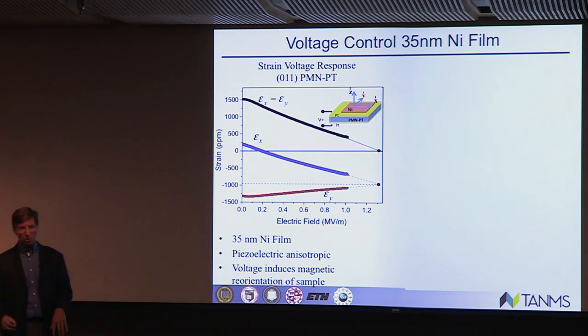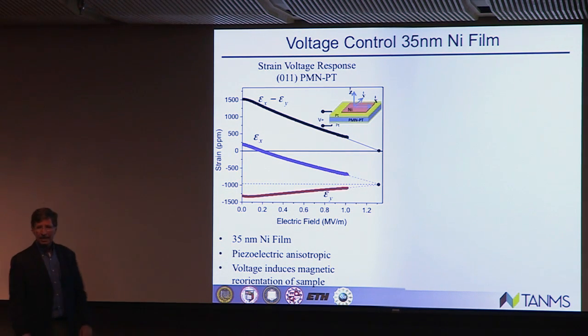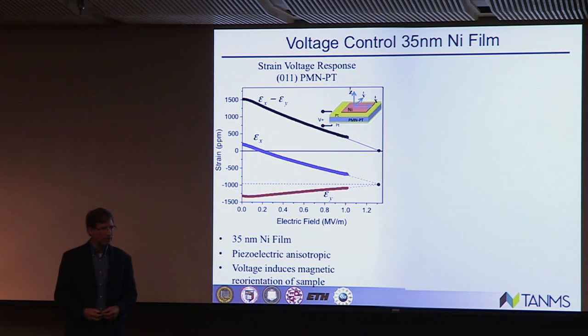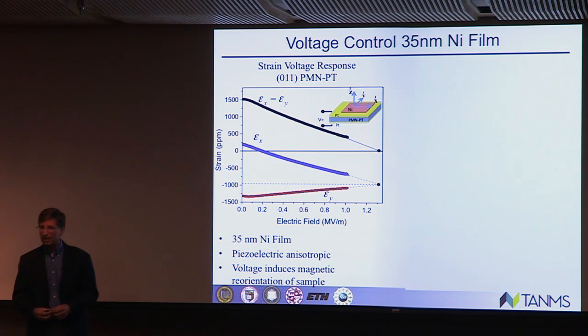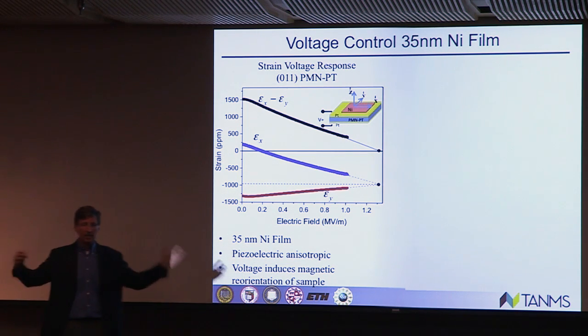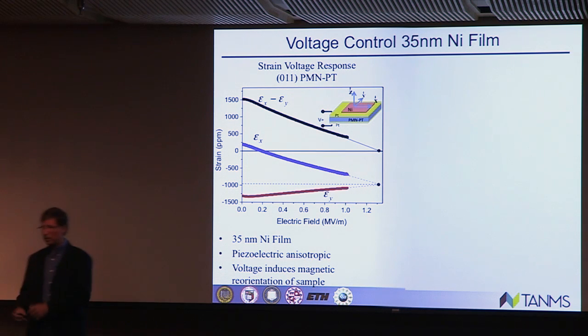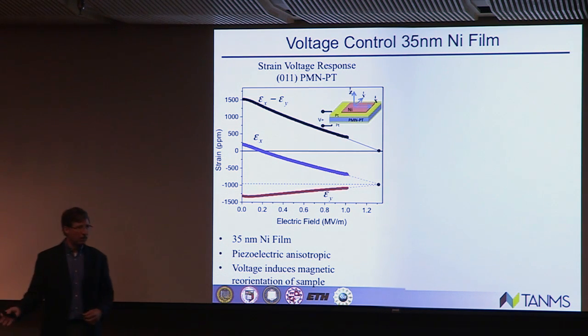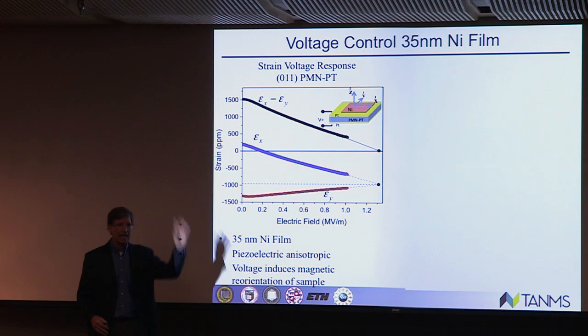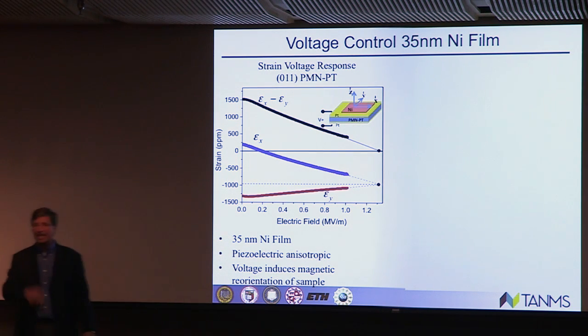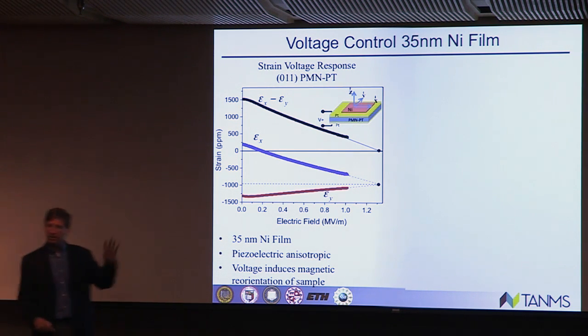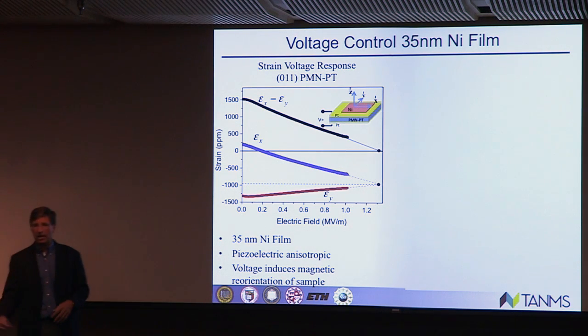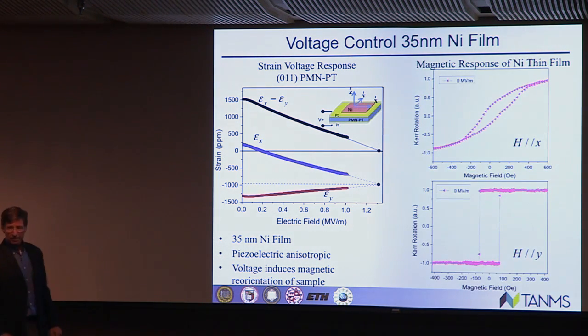Now that's very important. Now the other thing I want to point out is what magnitude strain are we looking at? Now some of you may not hear strain that often, so let's just talk about percentages. We're talking about 0.1% strain. Is that a big number? I'm going to argue that's really, really small. So we're not talking about these large percent strains that sometimes you see in the community. If you go fly an aircraft, you ask, well, how much strain was that aircraft designed to withstand? At least 0.5% strain. So if you put this on the aircraft, it's below that strain threshold. So now let's look at some data.